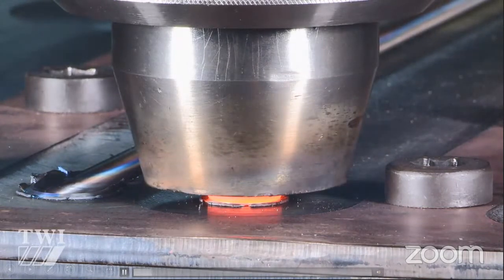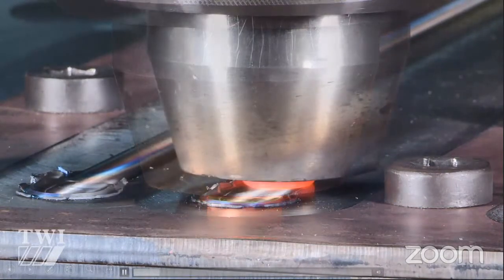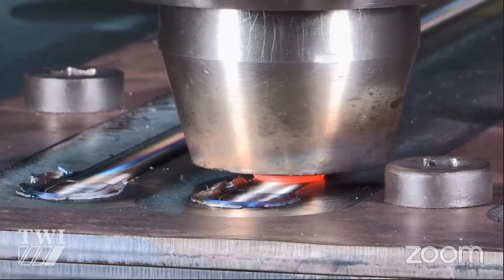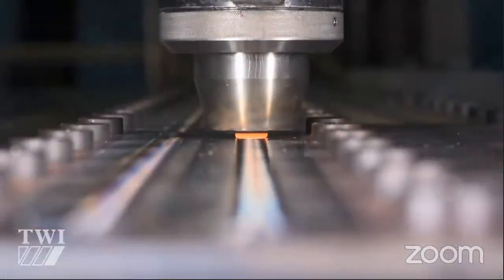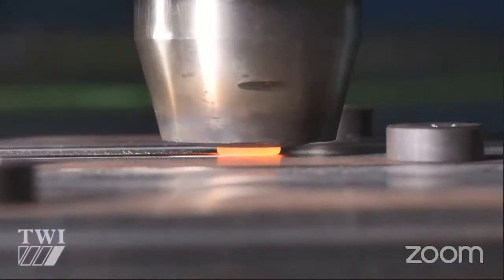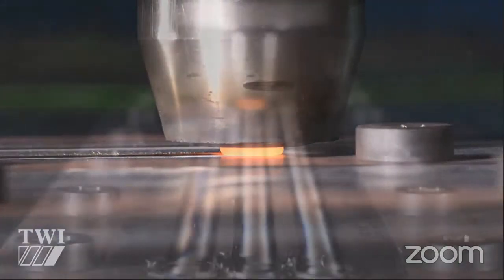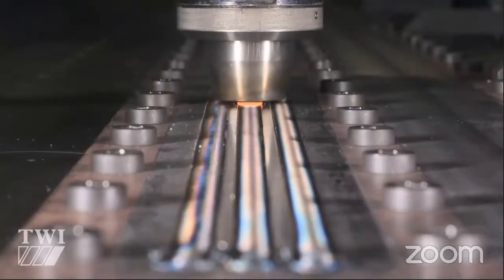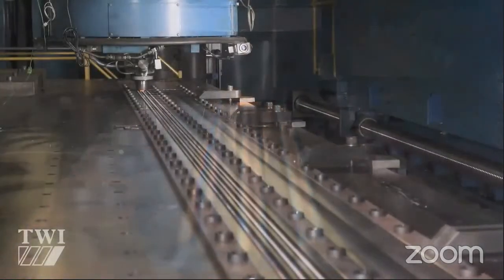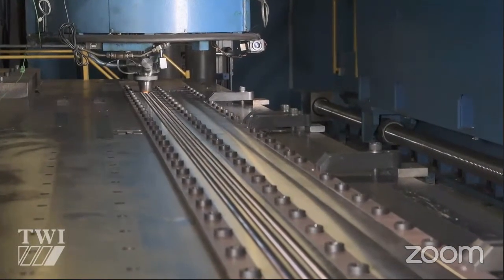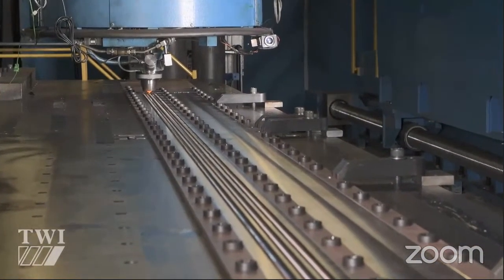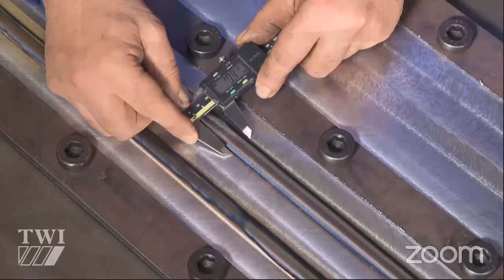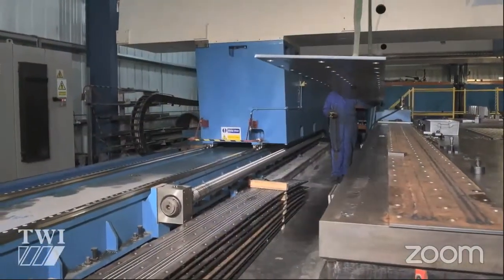So what we're seeing here is the tool slowly embedding itself into the steel plate, and it's now traversing along the surface. And you'll notice that because we're working at much higher temperatures in steel, the tool is now glowing bright orange, indicating that the tool is hot, but the weld itself is still solid, and the weld itself is not glowing. It's still a nice, strong weld. As you can see, we get a very smooth, regular, consistent surface, and the plates that we're welding are not distorted.